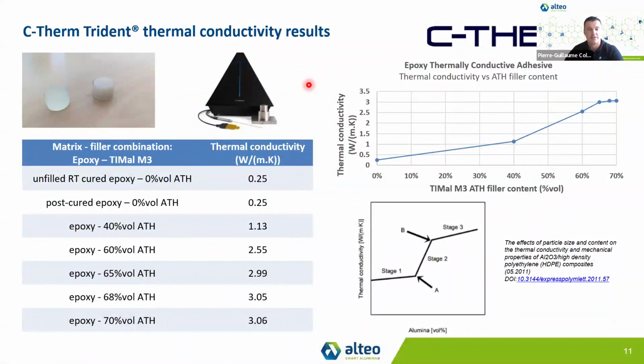And the other partnership we have conducted with C-Therm is about thermal conductivity. So again, we have made some specimens, unfilled epoxy, and in that case, we have made different specimens by increasing the filler content of TIMal M3. On the table, you can see the benefit of increasing the filler content. And we have achieved, for the higher amount, a thermal conductivity of around 3 watts per meter Kelvin. So again, this has been achieved only by using ATH.